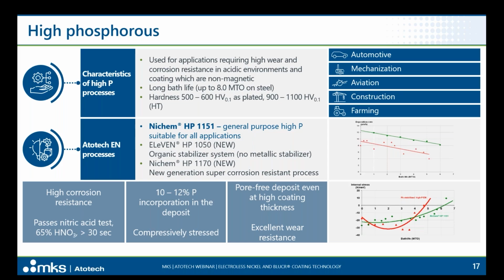So all these processes pass the nitric acid test for more than 30 seconds. We have 10 to 12% phosphorus incorporation in the deposit. We are compressively stressed until 6-7 MTO. We have a very good corrosion resistance using these processes because the coating is pore-free, and we have a very good wear resistance.